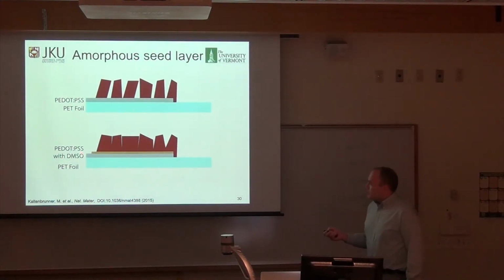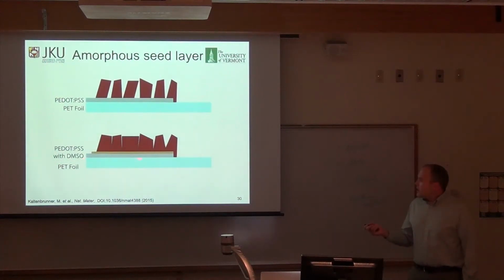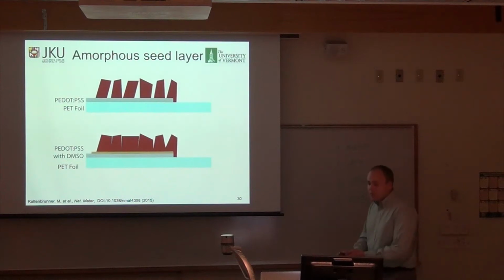What we found is that if we infuse the PEDOT layer with a very high boiling point solvent, DMSO - and DMSO is a good solvent for lead iodide - this layer retains the high boiling point solvent for days. It might never come out, we don't know for sure. But then when you put the perovskite on top of it, it maintains an amorphous layer right at the interface, and that causes the crystal growth to be much more compact, so that the gaps in between fill.